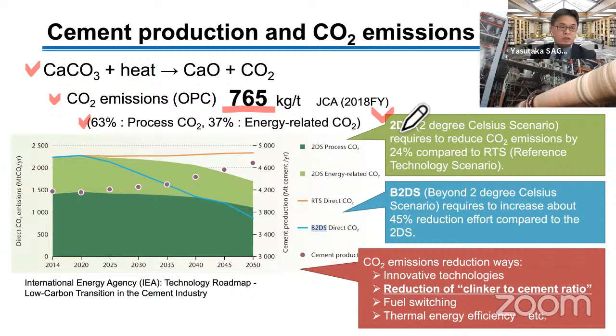In 2018, IEA published the technology roadmap for low carbon transition in the cement industry. This report is based on the roadmap to achieve 2 degrees Celsius scenario. The 2 degrees Celsius scenario requires reducing CO2 emissions by 24% compared to the reference technology scenario. And beyond 2 degrees Celsius, a very challenging scenario, requires about 45% more reduction effort compared to the 2 degrees Celsius scenario.